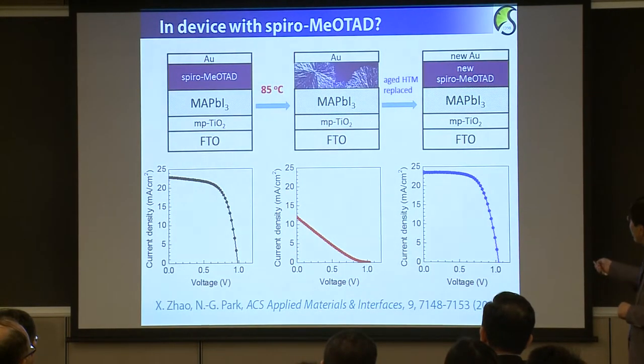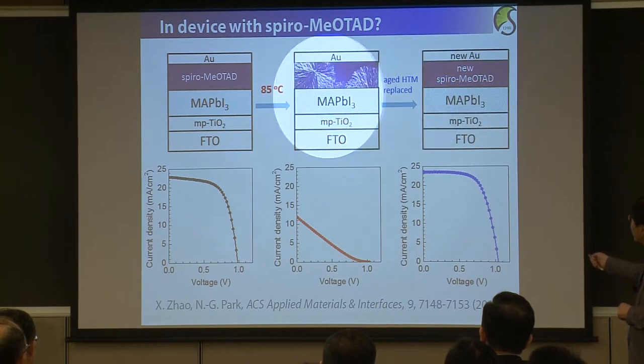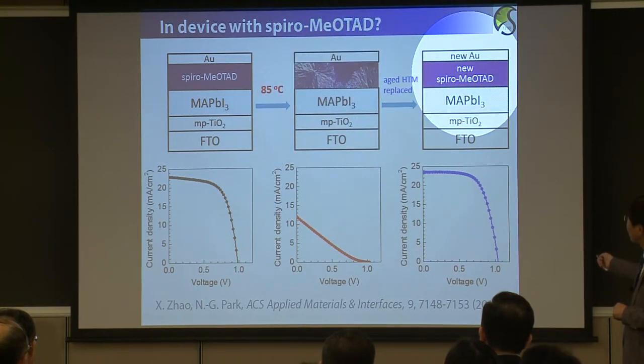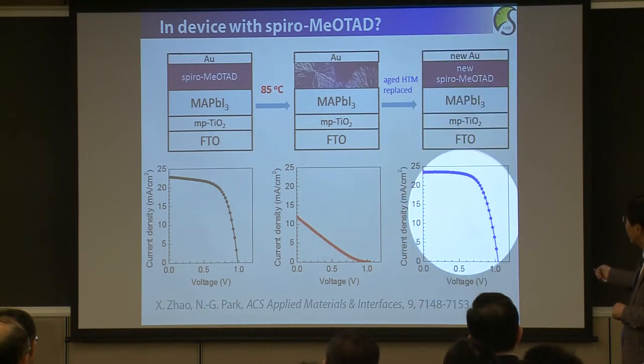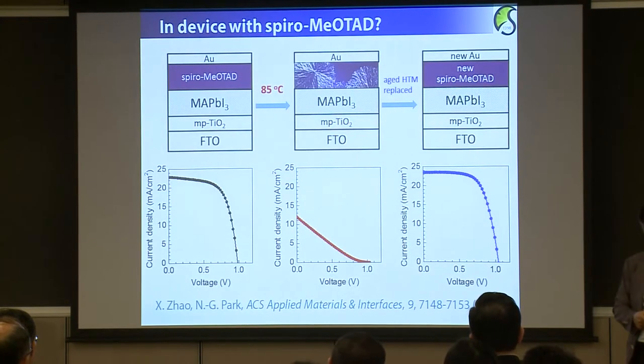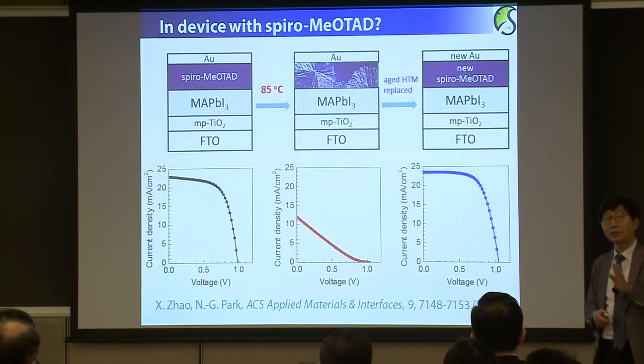So we replaced the aged spiro compound with a new spiro material, and then we found the recovery of the IV curve. So meaning that we have to find thermally stable hole conducting materials.